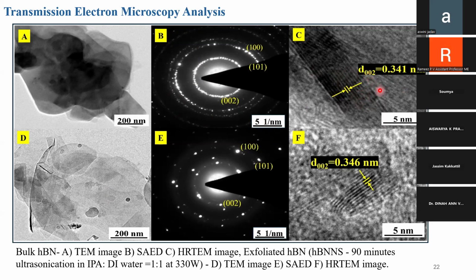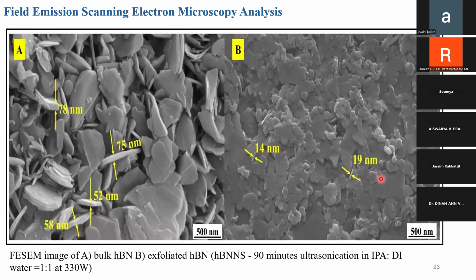Here you can see that the d-spacing of bulk HBN is 0.341, and the d-spacing of the hexagonal boron nitride nanosheets, the exfoliated one, is about 0.346. That means the so-called exfoliation is effectively carried out. That's what we can say. And not only that, it also tells you that the structural integrity is maintained. There are no defects in the crystallinity.